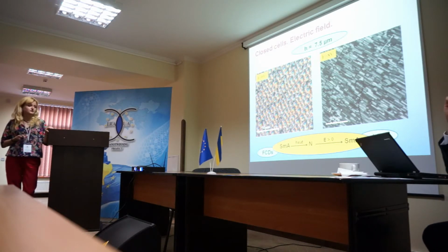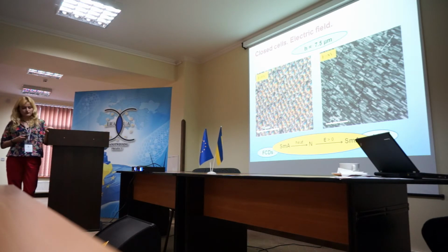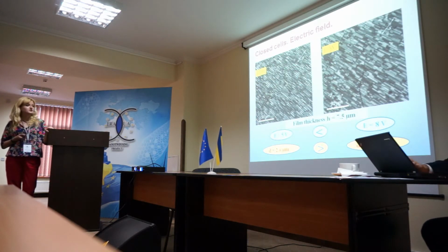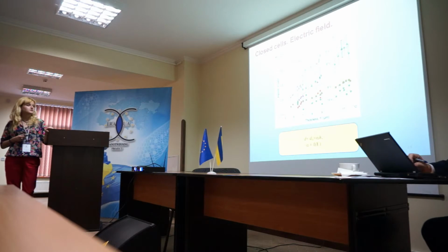We tried different cell thicknesses and different values of applied electric field, and it showed that for the same thickness of the cell, while increasing the voltage, we observed a smaller period of the linear defects. The dependence of the period as a function of the thickness you can see on this graph. It looks very complicated, as for each electric field value we have a different